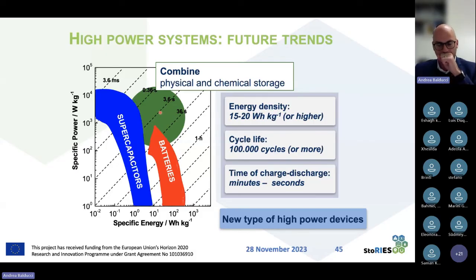To realize a system with the energy density that reached the target we discussed before, so 15 or 20 watt-hour per kilogram, or even higher. A cycle life which is higher than the lithium-ion battery, but a bit lower than the one of supercapacitor. But 100,000 cycles would still be a very, very good range. And time of charge and discharge in the order of minutes or seconds. So basically, you wanted to extend a little bit the time scale in which this high-power system can be used. So this was the idea, to try to realize devices that are in between, covering this green area, which is the area of interest.